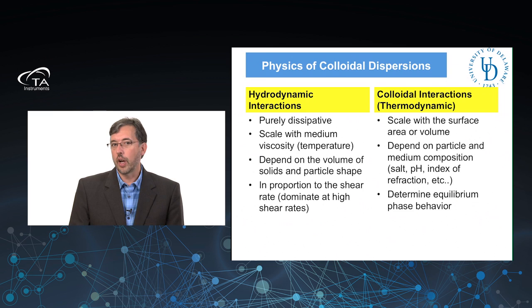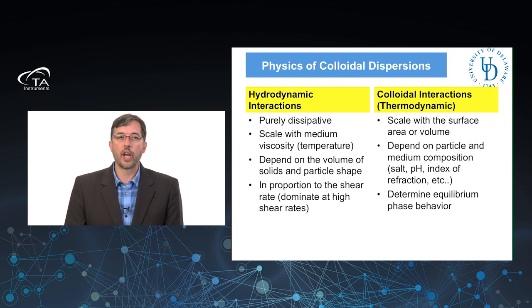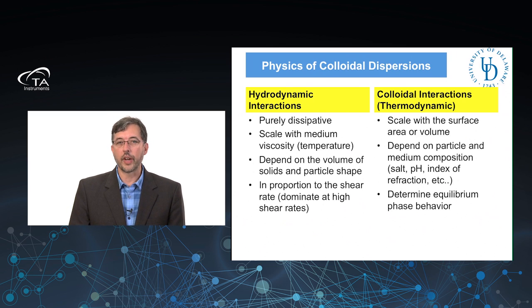They're always dissipative. They always cause an energy loss. That means they lead to G double prime contributions and not G prime contributions. They scale with the medium. They depend on the viscosity, if you will, of the medium. So if that's temperature sensitive, these will be temperature sensitive. It depends on the volume of the solids that are there, and it depends on the size and shape, particularly the shape and the polydispersity of the system, and in proportion to shear rate. That is, the forces are in direct proportion to shear rate. So if I turn off the flow, these go to zero. Okay? And that's one way to determine them. The colloidal interactions we've introduced, on the other hand, are very different, right? They tend to scale with either the surface area or the volume in the case of the van der Waals forces.